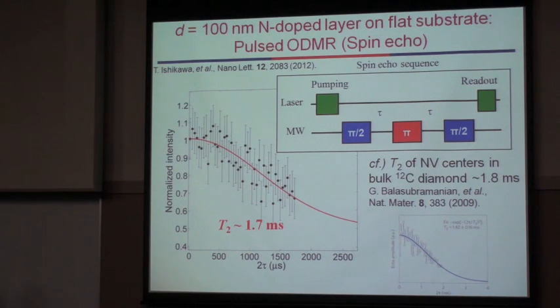This is a comparable value to the longest coherence time measured in isotopically enriched bulk diamond. So this result shows isotopic engineering is very important to obtain the long coherence time on NV centers.